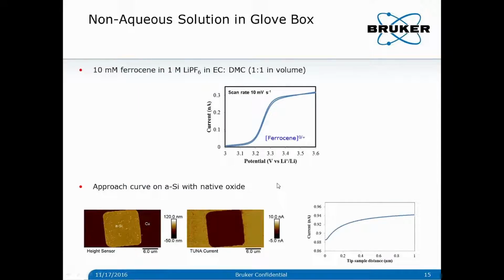And this is the CV curve using another redox couple, which is 10 millimolar ferrocene in 1 molar LiPF6 in EC/DMC. So this is a very typical lithium-ion battery solution. It has been shown by the Truhlar group that ferrocene has an electrode potential of about 3.3 volts with respect to the lithium reference, and we have observed the same result.